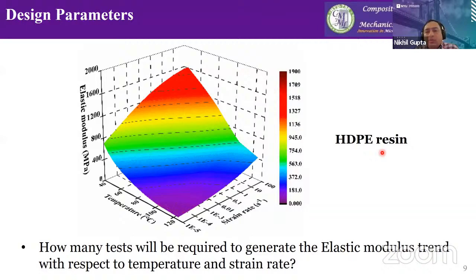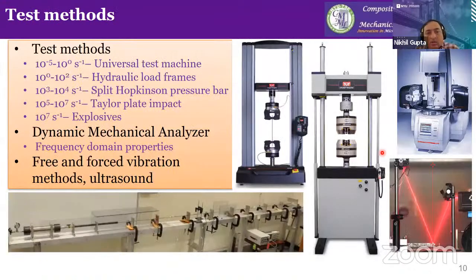Now, the other problem here is that not a single equipment can test all the materials from 10 to the power minus 5 to 10 to the power 4 or 5 that we are looking for. We have a range of equipment that we use for different purposes. So the universal testing machine, like the Instron machine here, can usually test from 10 to the power minus 5 to 1 per second. The hydraulic machines can go up to about 100 per second strain rates if you're lucky. Usually they go up to about 10 per second.